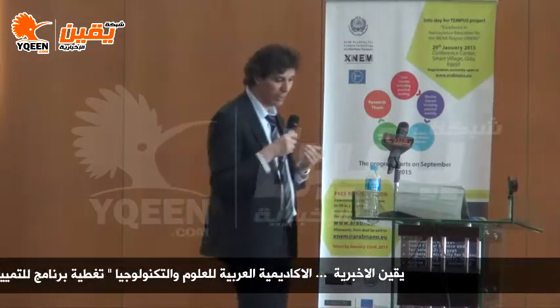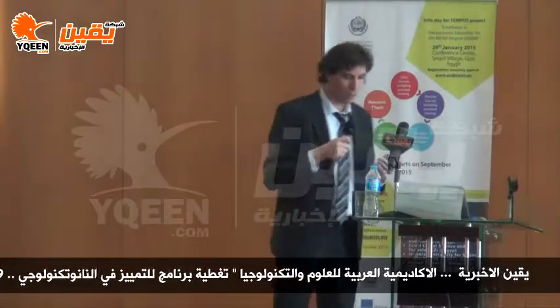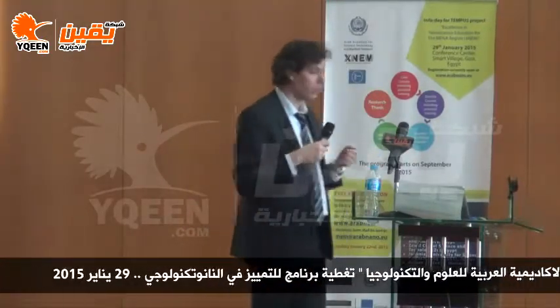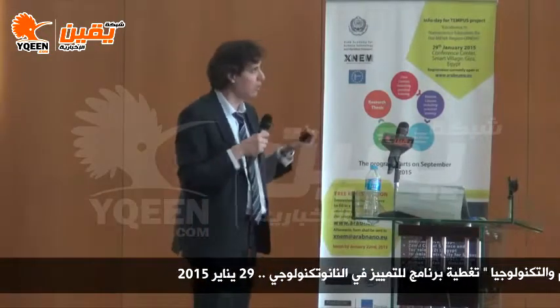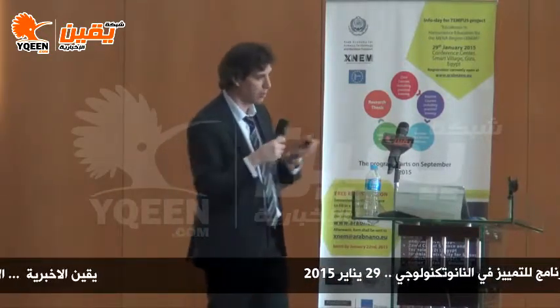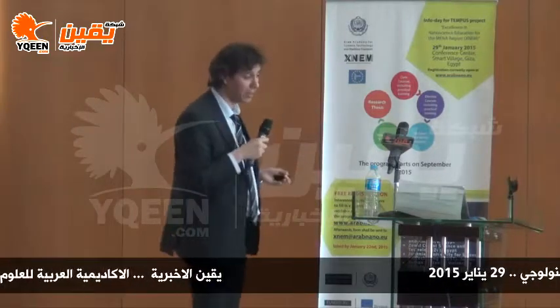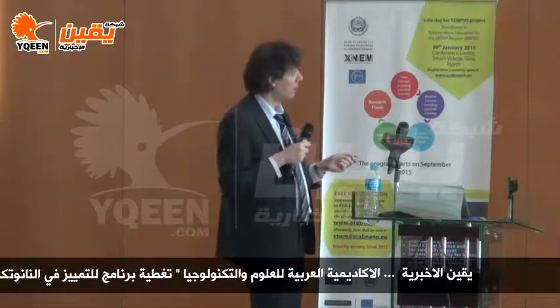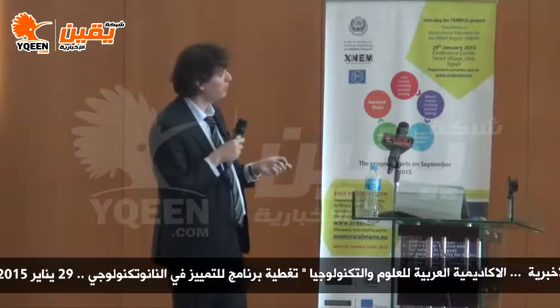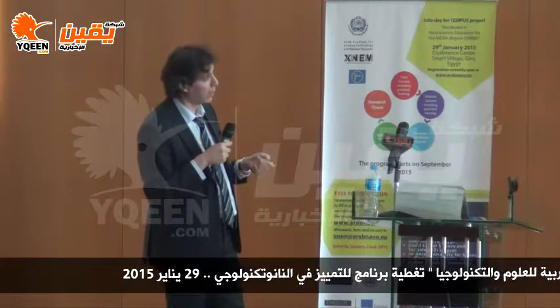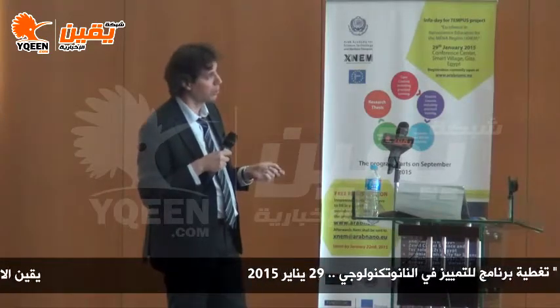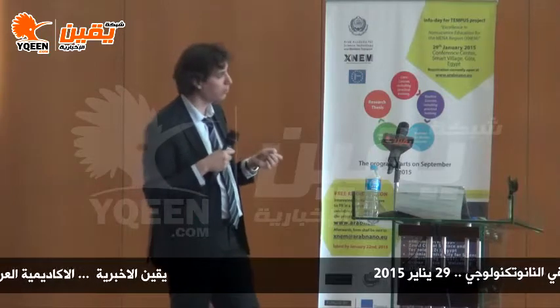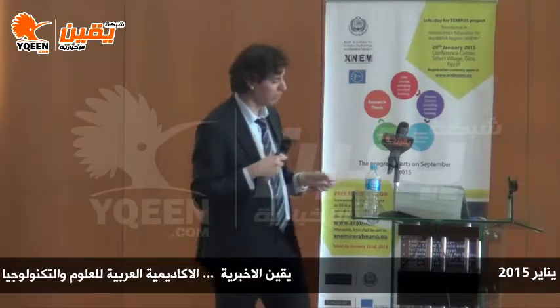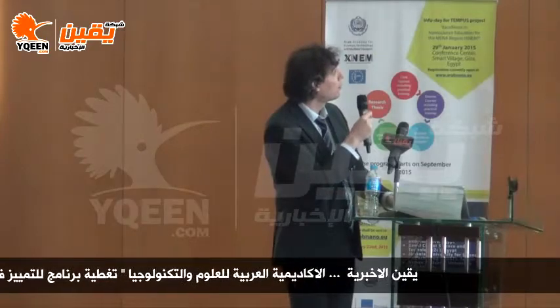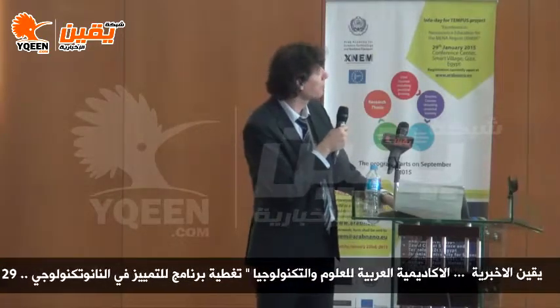So of course I mentioned heterojunctions or heterostructures to make devices. If you want to make a P-N junction, you need a P-type material and an N-type material, both of them semiconducting. In the case of diamond, by growth, we can only have P-type. And the reason we are not able to develop N-type is because the ionization energy of the N-type dopant within diamond is too large. Even by heating, it's not enough to activate. So this is one of the major bottlenecks that the diamond technology suffers from.